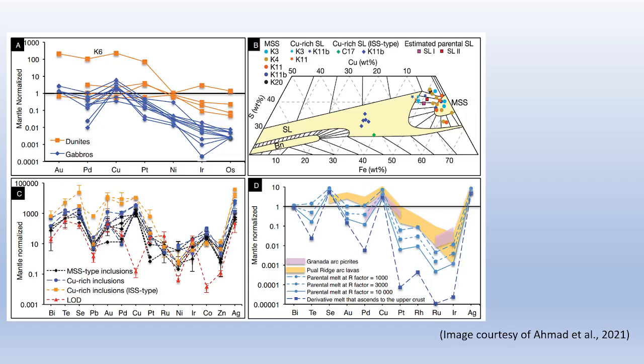Let's step back here and look at the bigger picture. How do the deep cumulates of the Chilas Complex compare to magmas that eventually form porphyry copper systems? Panel A lays the foundation. This plot shows whole rock metal contents normalized to the primitive upper mantle. Most gabbros sit low in gold and PGEs, as you would expect, but one sample, a dunite called K6, breaks the trend completely. It's off the chart, enriched by orders of magnitude in copper, palladium, and gold.